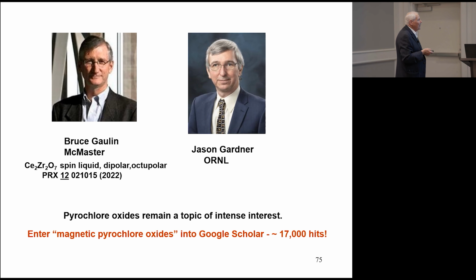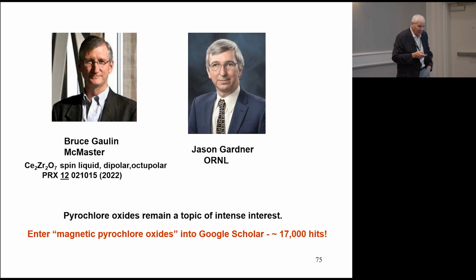Okay, so I just want to mention a couple of other collaborators before the last slide. Bruce Gaulin, a colleague at McMaster, has been with us from the very beginning. He's an expert in neutron scattering. And he's still studying pyrochlores, although I don't do it anymore. They published a very nice paper on cerium zirconium oxide, and they're claiming evidence for all of the buzzword topics these days. It's a spin liquid. For particular varieties, all kinds of spin liquids now, just roughly one for every theorist. It also shows dipolar and octupolar magnetic ordering. So you can get all kinds of stuff.